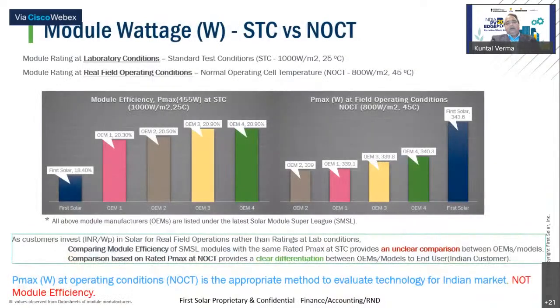So the nameplate power at 25 C in a controlled atmosphere is far removed from what the panel actually sees in real life. In the field, the panel is covered in dust. The atmosphere has humidity that changes, which changes the spectrum, and the panel operates at temperatures sometimes above 40 C. As the resistance of the material increases at higher temperatures, panel performance comes down. It is nowhere close to the label on the panel.